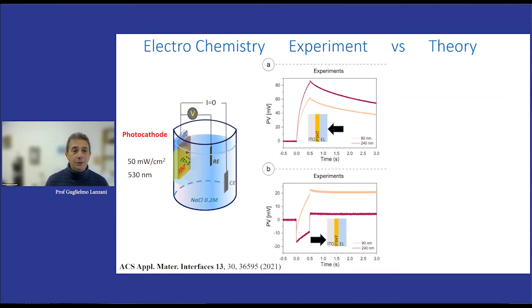And we have P3HT, which is the working electrode. There is a counter electrode and a reference electrode as usual. And we measure the open circuit voltage. So there is no current going through, okay? Now, if we shine light from the electrolyte side, we see a positive photovoltage at the ITO. When we do the experiment on the ITO side, we shine light on the ITO side, we see a negative photovoltage. However, the negative photovoltage in time evolves towards a positive signal.